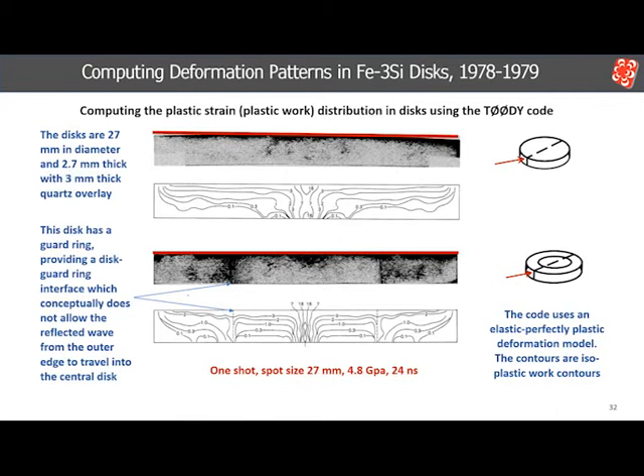TOODY now predicts a column of more intense deformation along the axis, as well as deformation associated with the internal interface of the guard ring. However, the most intense strain along the axis is at the top of the disc, not the bottom. The strain distribution at the guard ring interface is pretty much as predicted.